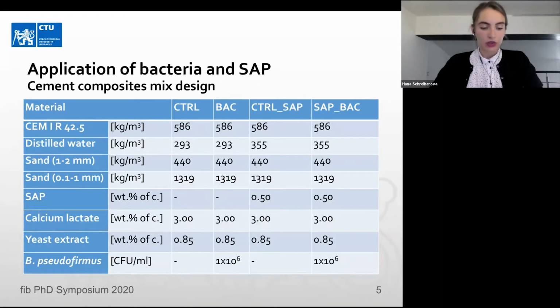In our paper, to determine the applicability of SAP in the bio-based self-healing concrete, 4 cementitious composite mixes were prepared, as you can see. All of them contain nutritional additives needed for the biocalcification process. That's the calcium lactate and yeast extract. And their composition and dosage were based on the studies described elsewhere in the literature. The series BAC and SAP BAC further contained bacteria, specifically Bacillus pseudofirmus, and the series control SAP and SAP BAC were further enriched with 0.5% of SAP by weight of cement.